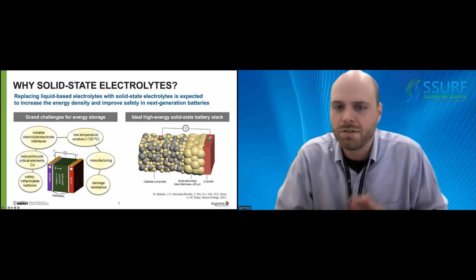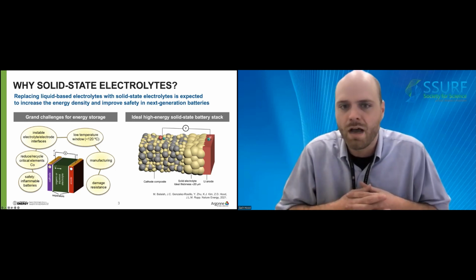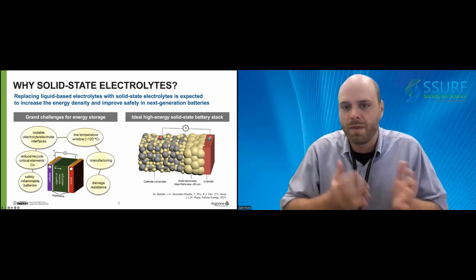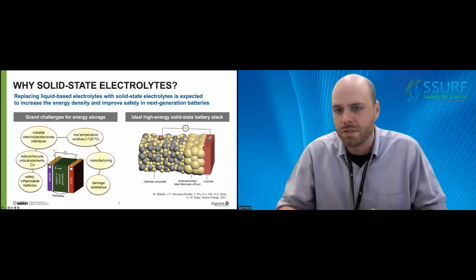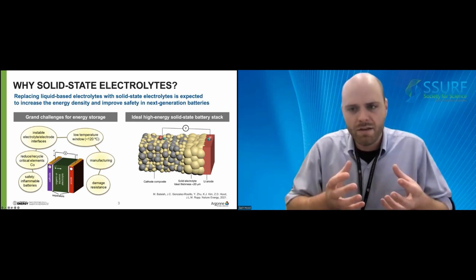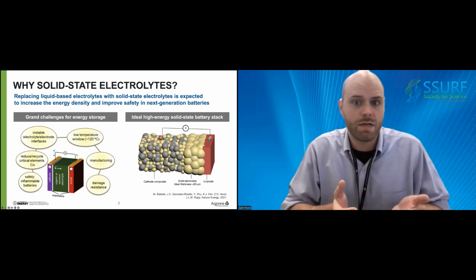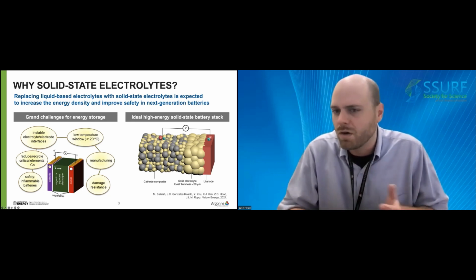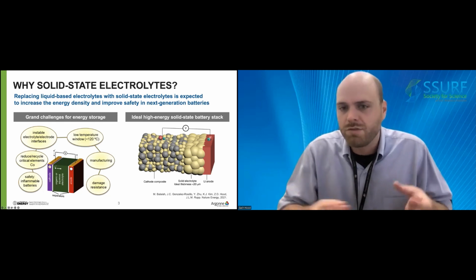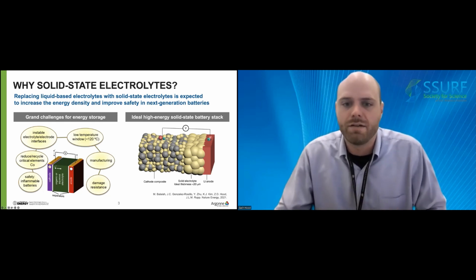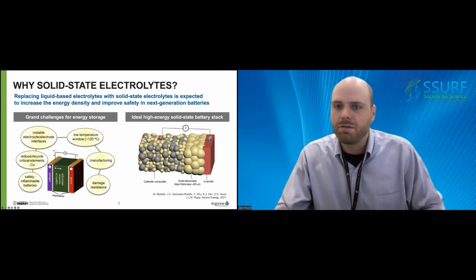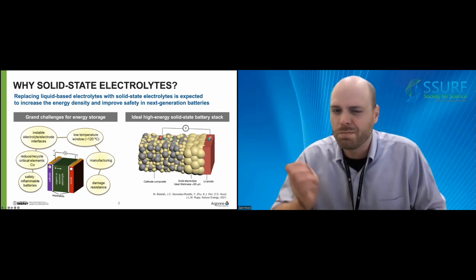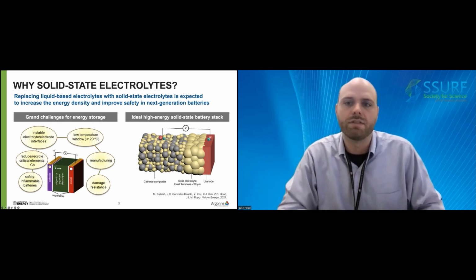It has your anode, which is generally a carbon-based material that theoretically allows for one lithium ion to be stored per 6 atoms of carbon. Second, you have your cathode, which is generally a lithium transition metal oxide, such as lithium cobalt oxide, that allows for intercalation of the lithium ions into the layers. And lastly, you have a liquid-based electrolyte, which is generally a lithium salt dissolved in an organic solvent.